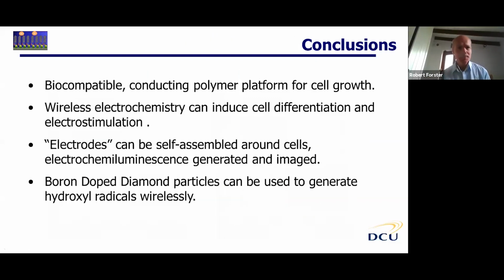So this is probably the most exciting slide of all, the conclusions. Working very closely with Junshen, Jilan, and Shunyan down in Wollongong, we really do have a nice conducting polymer platform that cells can adhere to, which preserves the electrical connection so we can induce a potential within that electrode, have it transfer faithfully to the growing cells on the surface, and use that potential to stimulate the cells.